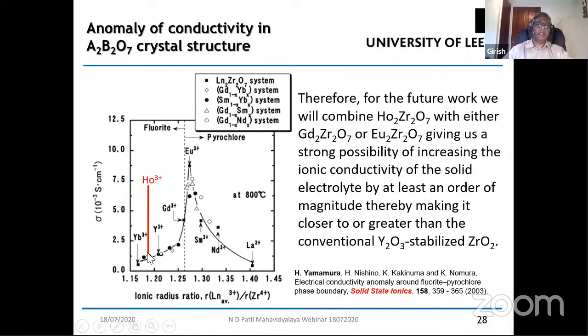So if you look at the ionic radius of holmium 3+, it sits somewhere here. Now, there was a paper published, I think, in the early 90s by a Japanese group in Solid State Ionics. And what they showed is very interesting, and that is what is quite promising about this material. So what you see is that the holmium zirconate that we prepared sits somewhere here, and it has conductivity that is not very promising at the moment. This particular graph shows conductivity as a function of ionic radius.